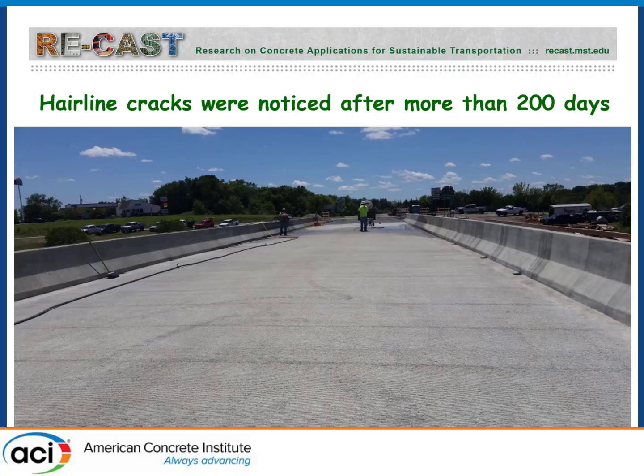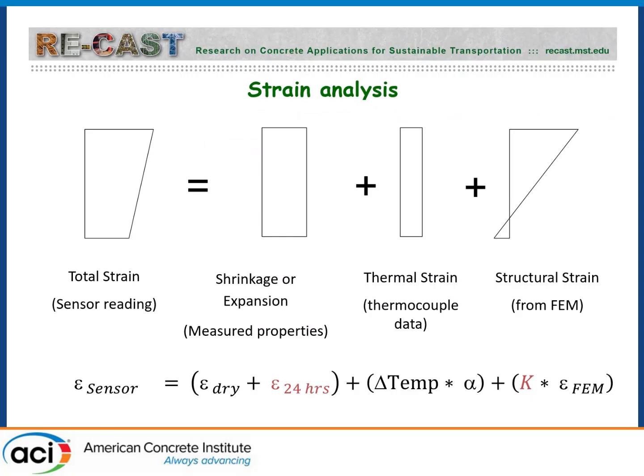We call those hairline cracks. They were very, very small around the middle diaphragm, about 10 feet in each direction. But beyond that, there was no cracking, very little pitting of corrosion on the surface. The surface is how it was cast, after screeding, so it's a very nice surface. And I go there a couple of times a semester when I go to visit MoDOT, and I stop and put my hard hat on and take a look, and it's doing very well.